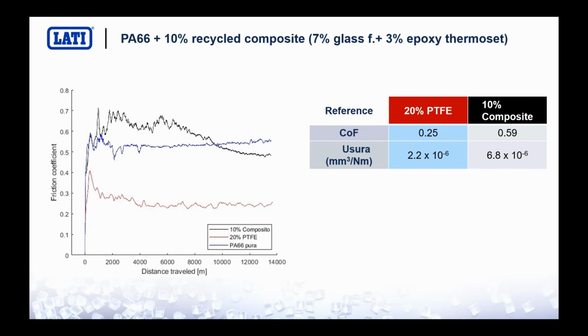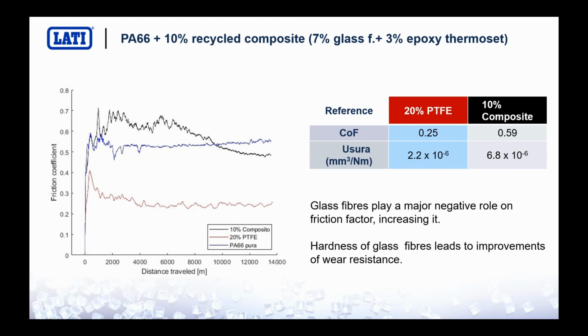Then, as I already mentioned, we analyzed also the behavior of some recycled composites, very interesting also from a sustainability point of view. In this case, we tested recycled composites made of glass fiber and epoxy thermoset. We know from the literature that glass fiber helps to improve the wear resistance, and this is what happened because we lowered the wear factor a lot. Even if, from a friction point of view, the glass fiber played a negative role, and they increased the friction coefficient of the unfilled polyamide 66. So in this case, this material can be good, but only from a wear resistance point of view, not for the friction.